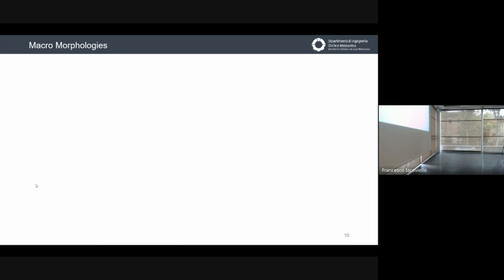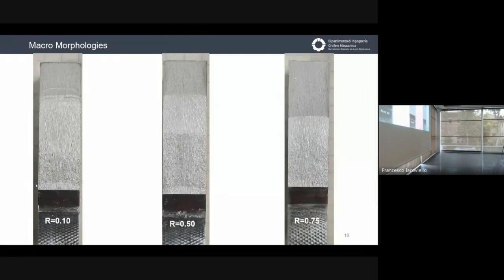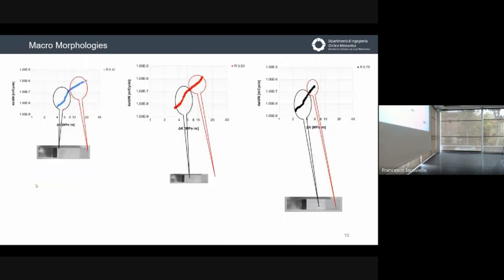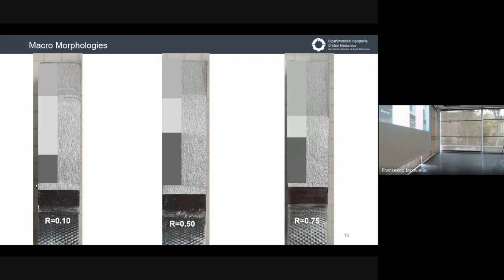What happens in terms of macro morphologies? These are the pictures taken on the surface of the specimen. This is the pre-crack obtained by the normal procedure in ASTM E647. But here we have a region characterized by a dark green region whose intensity fades to white. Here we have a sort of white region, and then the static fracture at the end of the surface. This is the situation for R 0.1, 0.5, and 0.75. And the white zone decreases in the higher load ratio.